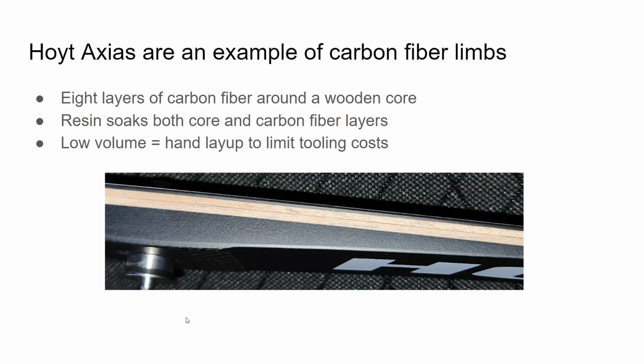Here's another close-up look at the Hoyt Axia. So as you can see, there are several layers. This thin layer at the bottom is made up of 8 layers of carbon fiber composite. Then there are a few wooden layers, shown here, 2 brown and 1 black, and another 8 layers of carbon fiber composite on the front of the limb. This system is made with the same resin soaked throughout the entire system. This helps bind the layers together and adds extra strength.